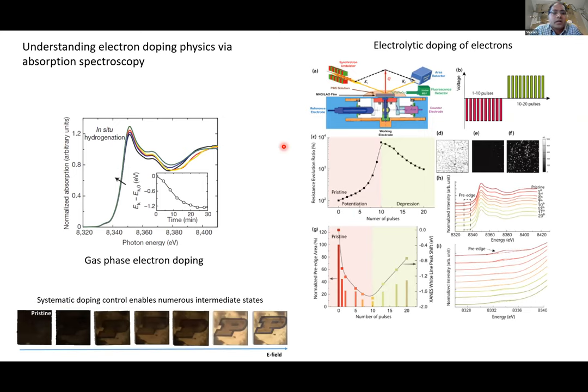Okay, so this is where Argonne comes in, and we have some absolutely wonderful collaborations over the years. What we have been able to study is adding and removing these electrons from these compounds very systematically. And we have done this through gas phase, liquid phase, solid state, all kinds of different interfaces to understand electron addition. So this is just one example, exactly in the context of neuromorphic computing. We are applying electric voltage stimulus to this nickelate, and then we are watching the electrical resistance change. And simultaneously, if you do X-ray absorption spectroscopy on these same samples, you can very carefully extract the nickel 3+ to 2+ ratio as you add and remove electrons, or hydrogen in this case. I'm sorry, electrons, to the compound. And so you can watch potentiation and depression happen along with the electronic structure change.